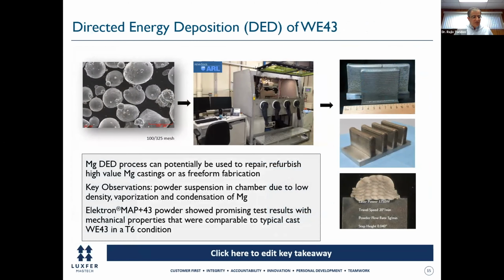On the directed energy deposition side, we were looking at the ability to potentially conduct free-form fabrication using WE-43 powders. The picture on the right shows the kind of parts that we were able to make. These were simple coupons, but they were about 12 to 15 centimeters long by about 6 centimeters high, which allowed us to pull tensile bars in horizontal and vertical directions and demonstrate what the potential feasibility of that process would look like. But again, there are challenges which have to be overcome, which has to do with not only the vaporization and condensation of magnesium, but also the powder suspension that you see when you're trying to feed the powder through a nozzle.